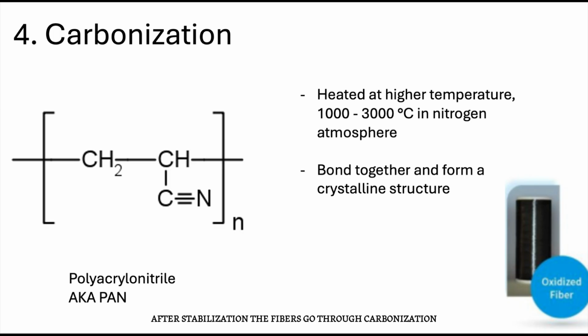After stabilization, the fibers go through carbonization. They are heated to very high temperatures, typically between 1,000 and 3,000 degrees Celsius, in a nitrogen atmosphere. During this process, non-carbon atoms such as hydrogen, oxygen, and nitrogen are released as gases, leaving mostly carbon atoms behind. These remaining carbon atoms then bond together and form a crystalline structure that aligns parallel to the fiber axis. This alignment gives carbon fiber its high strength and stiffness.